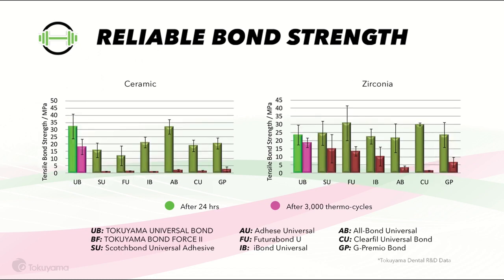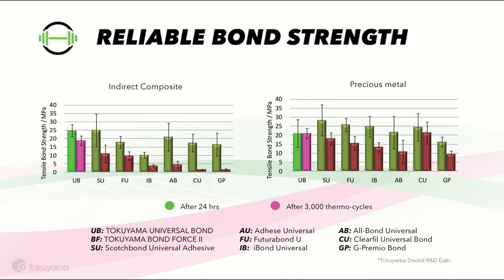Here we see the bond strength to ceramic and zirconia, which are the most used materials for veneers, crowns, and bridges. For these materials, you can see that Tokuyama Universal Bond provides the highest bond strength after 3,000 thermal cycles. Here are some more comparisons for indirect composite and precious metals. As we can see, the results from this study shows that Tokuyama Universal Bond demonstrates superior bond strength to all restorative materials.